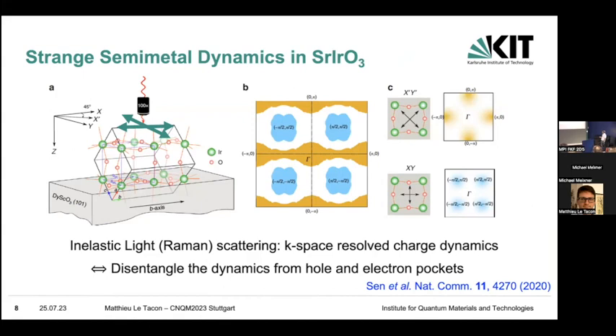And the idea is actually quite simple. We can do inelastic light scattering, so Raman scattering, which is historically something I've been doing for fun. So we have a film of strontium iridate grown here on this dysprosium scandate substrate. It could be another substrate, but it happened that it worked quite well with this one. And you can shine some light, with polarized light, and analyze the energy distribution of the scattered light.